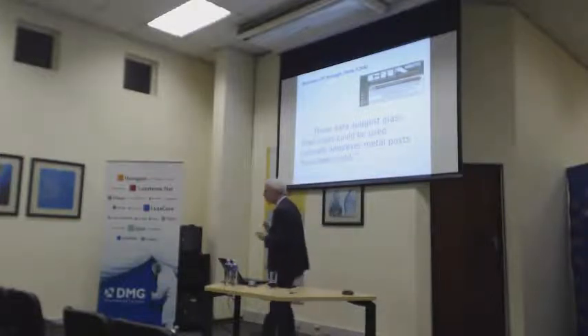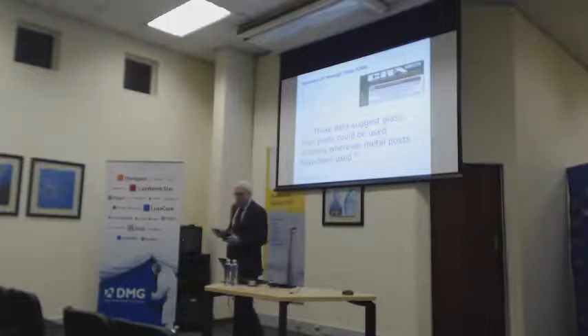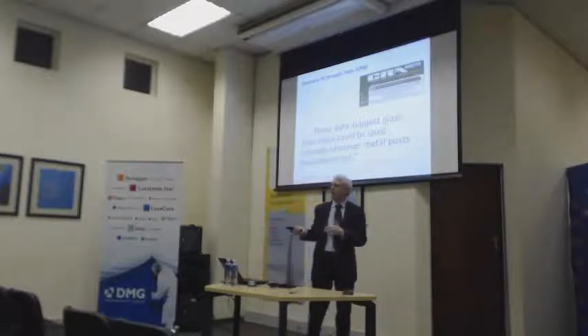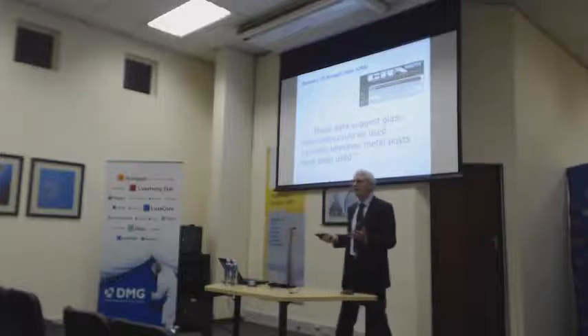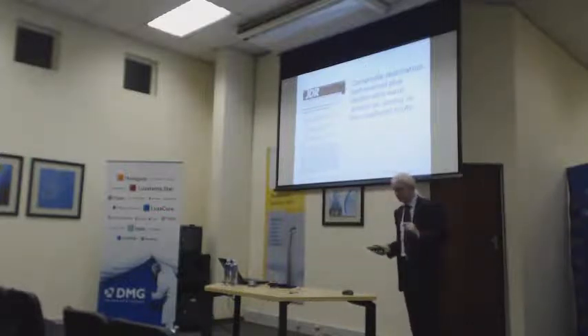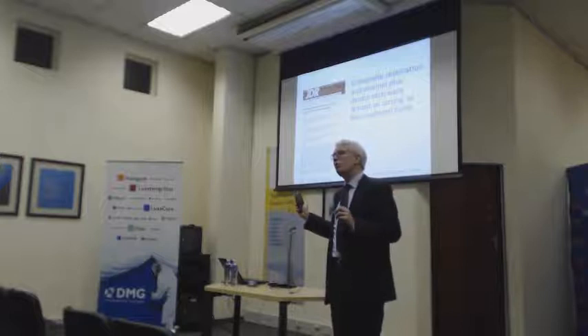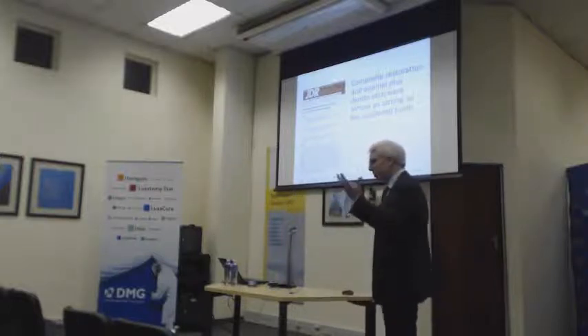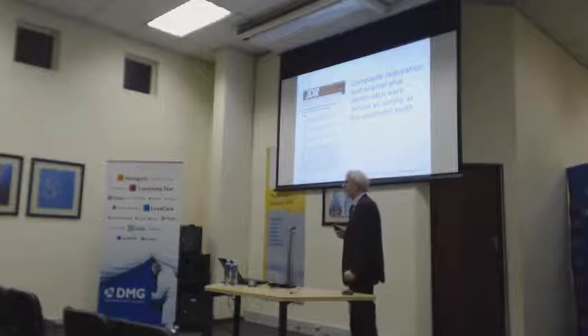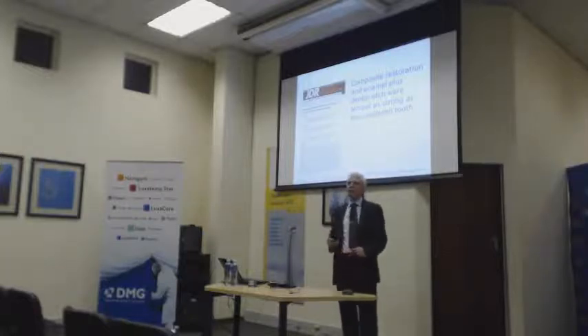And the results are very, very clear about this study. This is only part of it. The quintessence was that whenever you're using metal posts today, you should switch to glass fiber posts. That is the advice you get out of this. And to just reinforce this a little bit, there's another piece of research that also confirms that when you're using a composite buildup and a proper bonding procedure that worked with this specific combination, that was almost as strong as the unaltered tooth structure. So that is very, very good news.